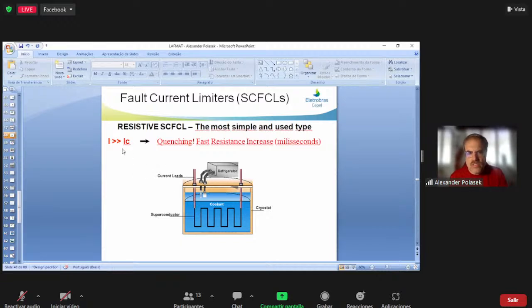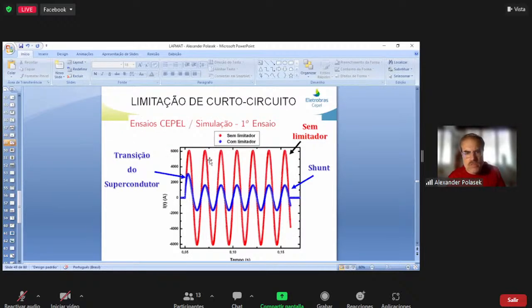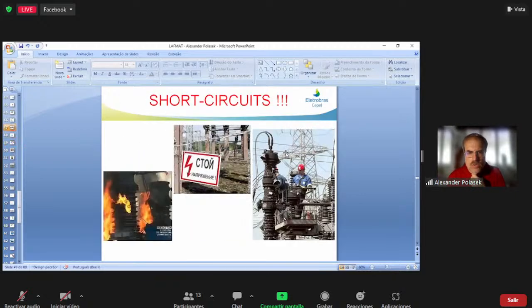And when you have a short circuit, it quenches. And in milliseconds, you have a transition from superconductor to a resistive material. What happens is this. The red curve shows the short circuit without the fault current limiter. In the blue curve, you can see what happens when you have a fault current limiter. And it's very nice because you have a circuit breaker here, but it will protect the circuit breaker, because if the red curve is above the circuit breaker capacity, this will happen.